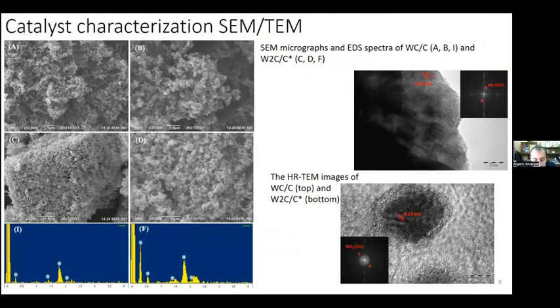According to the SEM micrographs, the sample has a grain structure with an average grain size of approximately 50 to 90 nm. The area spectra of tungsten carbide samples contain two elements, tungsten and carbon, whereas the activated samples contain oxygen in addition to tungsten and carbon.